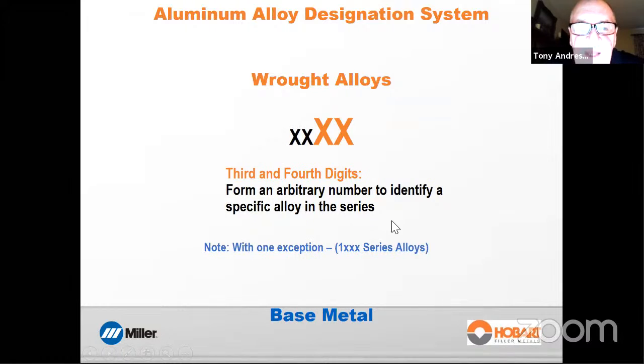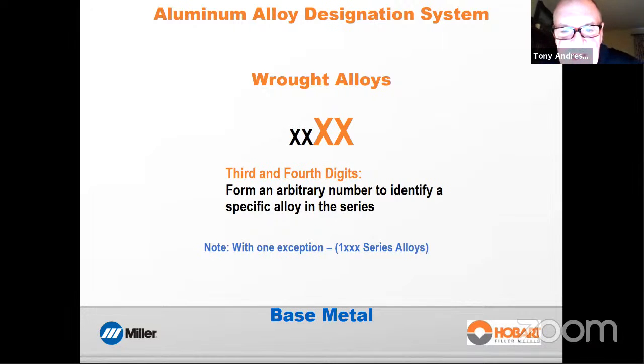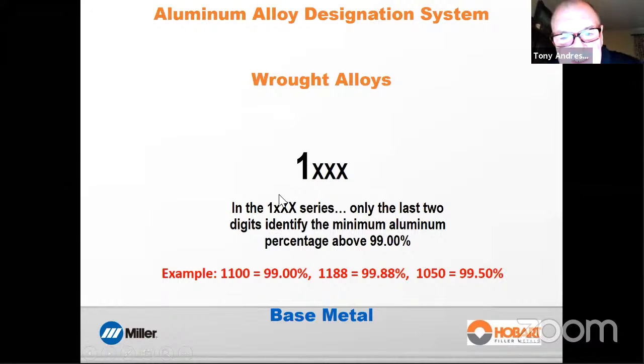Okay. The last 2 digits in the 4-digit numbering system don't mean anything. They're just an arbitrary number assigned by the Aluminum Association in order to track the alloy in the register. However, there's one exception, and that's the 1000 series alloys. So what is that exception? In the 1000 series, the last 2 digits indicate the purity of the alloy above 99%. And in the examples here, we see 1100 is 99.00%. 1188 is 99.88% pure. 1050, 99.50% pure. So that's the only time those last 2 digits mean anything.